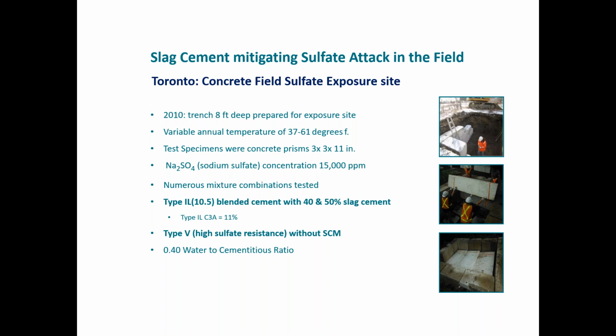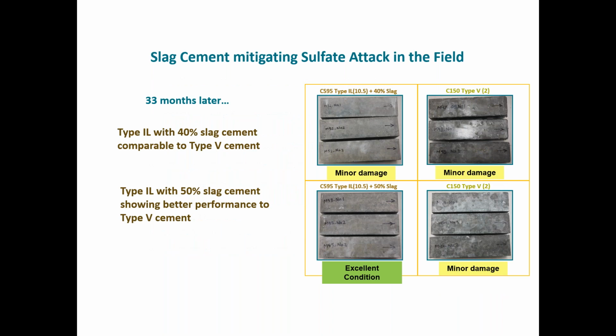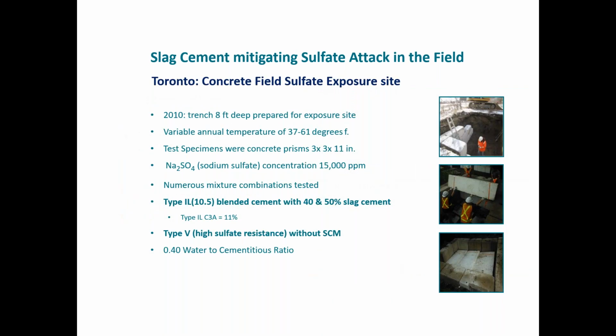So we're talking about field exposure sites. I'm going to glaze over this, but essentially this is an experiment that was done. There were multiple scenarios. They were looking at Type IL cement and type 5 cement, the Type IL cement having 40 and 50% slag, which is fairly similar to what I showed you in the previous slide. Their question is, can we get good sulfate resistance? So they made these samples, they bury them in the ground, and they manipulate the sulfate levels, and then they pull these things out and visually inspect them. So next slide.